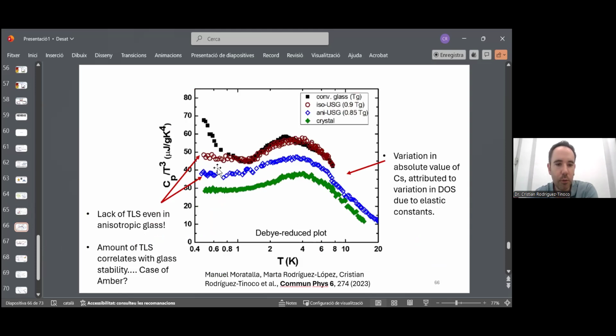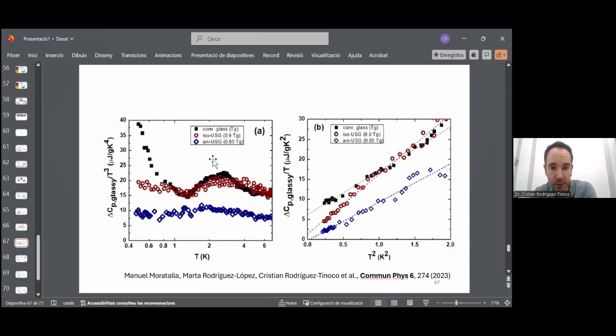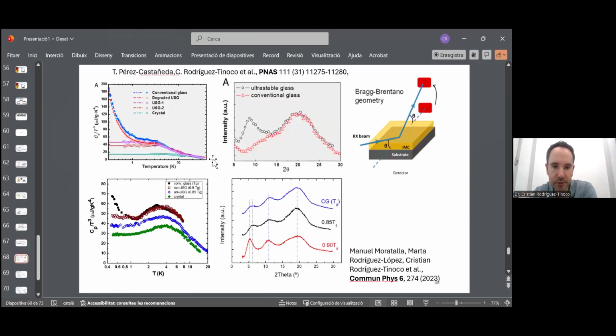And what can we see when we do the same? So we see that there is a lack or a strong reduction, let's say, of TLS in both systems. Even in the isotropic ultrastable glass, S equal to 0, remember, so no orientation, we still have a practically 0 amount of TLS compared to the conventional glass. You see here? So what does it mean? It means that indeed the disappearance of TLS is not due to the orientation of the glass, but it has to be due to the density of the glass. Okay, so these are different representations.